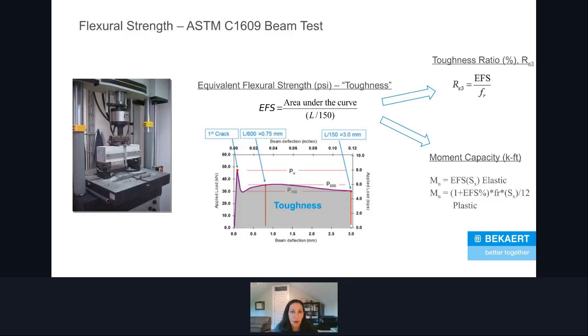Another option is to use an RE3 ratio or percentage, which is the equivalent flexural strength divided by the modulus of rupture. So that might be 30%, 40%, 50%, or the moment capacity. And it'll depend on whether you're doing an elastic analysis or a plastic analysis, which we'll come to in a few moments. But generally, that's going to be dependent on that equivalent flexural strength and this section modulus. Now, these are three of the most common performance specs that I see. They're not the only ones. There are a couple of others. So basically, we just want to pick at least one as a way to evaluate this post-crack flexural performance. And this is true of any kind of fiber reinforcing that is claiming that they have post-crack flexural properties. These are the things that you're going to be looking for.